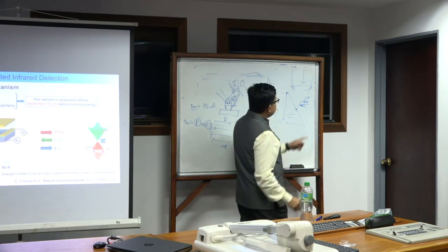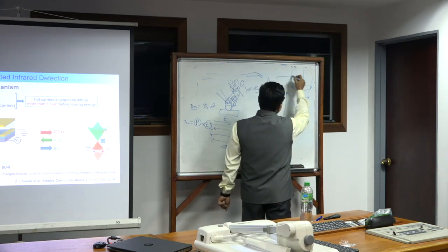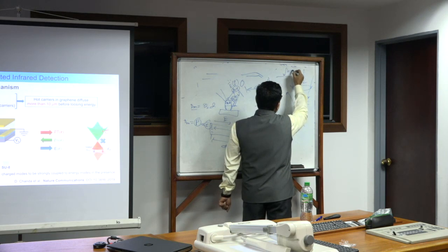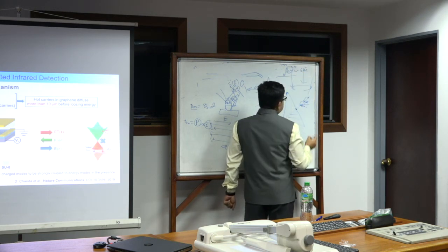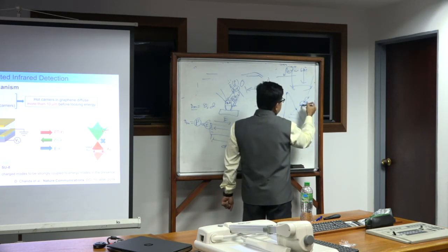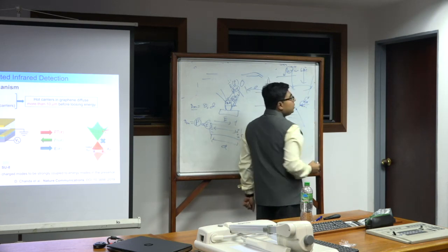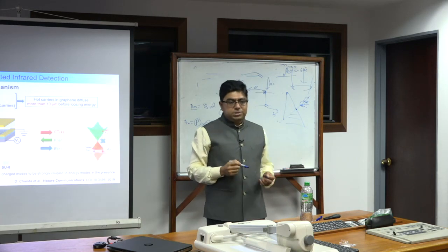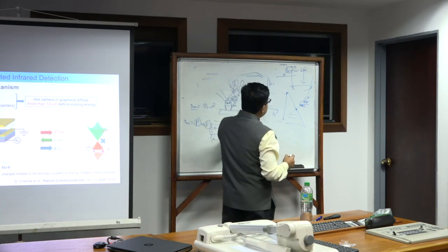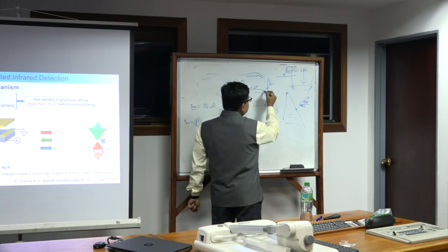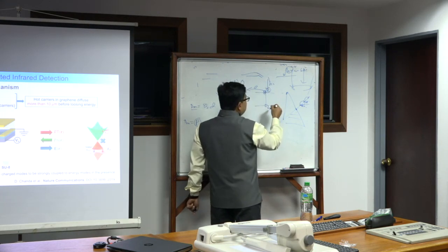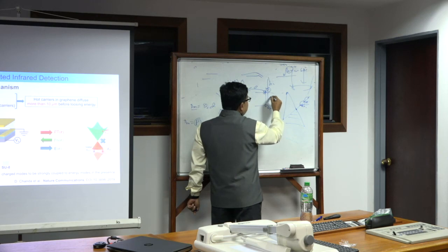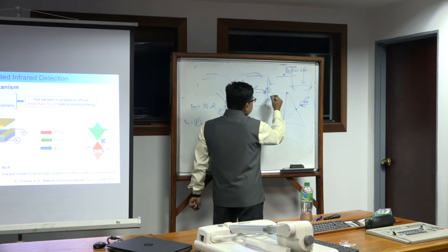That means even if I send photons onto a graphene sheet and absorb 60% of the light, they create carriers momentarily, but they recombine quickly because their energy gap is very small. For a normal semiconductor, there is a band gap. You create the electron here and hole here, and even at the same location, the huge energy barrier means they cannot recombine.